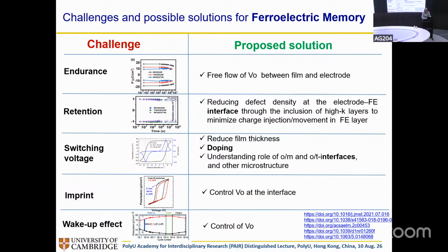So again, the challenges are similar. On the left-hand side, we see all the problems, well, the requirements: endurance, retention, switching voltage, slightly different things here. We've also got imprint and wake-up effect. Imprint is how the ferroelectric loop becomes shifted. If you move some vacancies and they get trapped at one of the electrodes, that can cause the loop to be shifted. And there's also the wake-up effect. Often these ferroelectrics don't work at the start. You have to apply voltage to wake it up. You have to change the oxygen, move the oxygen around before it becomes ferroelectric. So all these things are there, and many of them relate to control of the vacancies and control of the concentration. So that's where we're at.